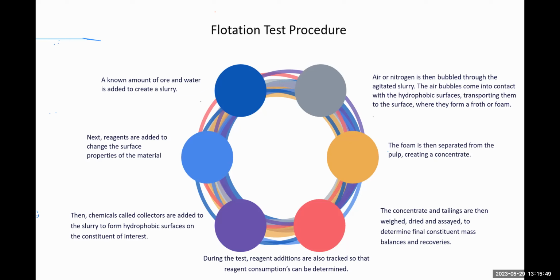When we say hydrophobic surfaces, it does not get itself attached to the solution, because hydrophobic does not react on its own. It does not love anything. So it's easy for this hydrophobic nature to just come out from the solution and then you scrape it out. Now, air or nitrogen is then bubbled through the agitated slurry. The air bubbles come into contact with the hydrophobic surfaces, transporting them to the surface where they form a froth or foam.